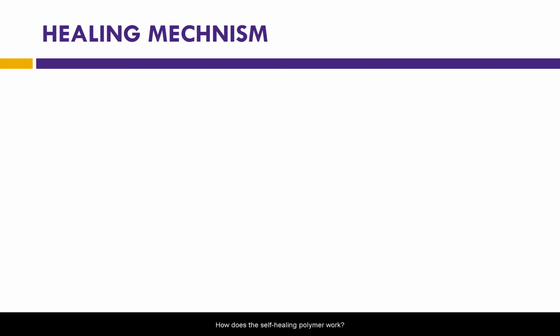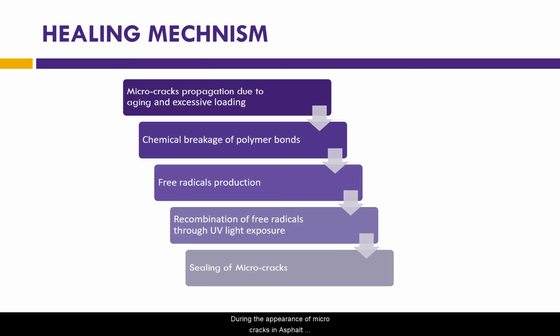How does the self-healing polymer work? During the appearance of microcracks in asphalt pavement containing light-activated self-healing polymer, different chemical bonds in the polymer will be broken. Consequently, the breakage of the bonds generates unstable free radicals. These radicals will recombine through UV light exposure. During the recombination, the radicals will repair the damaged area of the asphalt pavement.